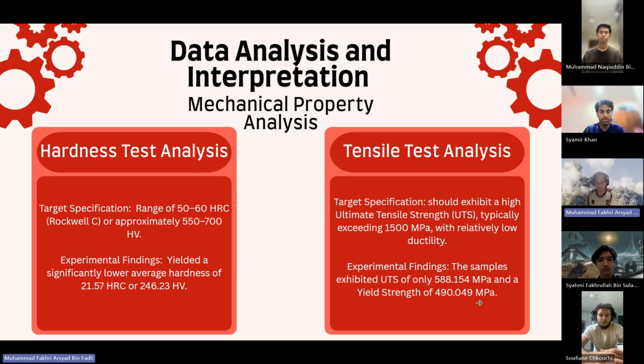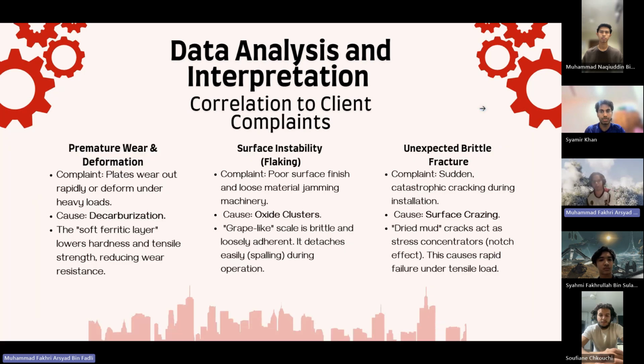From this analysis, there are several possible complaints from the company, the first one is premature wear and deformation. The complaint is that the plates wear out rapidly or deform under heavy loads, which is caused by decarburization, the soft ferritic layer, which lowers hardness and tensile strength and reduces wear resistance.